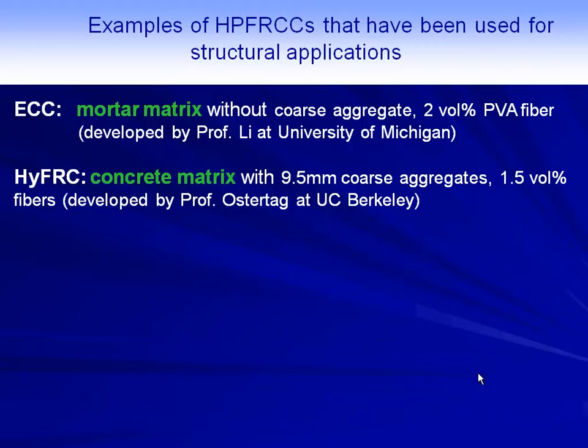And there's another one we looked at, which is my own material here, hybrid fiber reinforced composite, which is a concrete matrix. So it has coarse aggregates in there. The total volume percent is 1.5. And one thing I want to point out, we specifically wanted to have a concrete matrix. Why? It was so much more difficult to get these kind of characteristics of strain hardening, deflection hardening in a composite with coarse aggregates. But we wanted specifically to do that because we want to avoid the shrinkage and we want to avoid creep. And the best way to do that is to have your coarse aggregates in there.